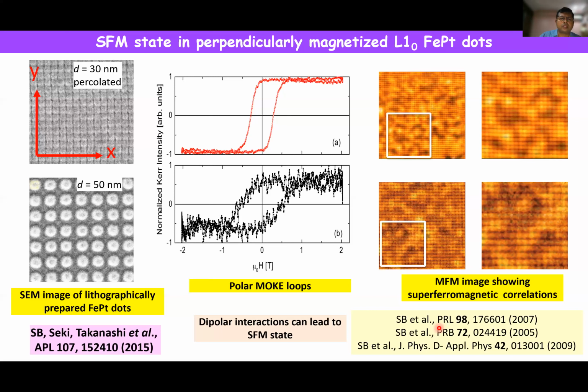So here I just quickly give a one-slide summary of some of our work in the so-called superferromagnetic domain state in magnetic dot arrays, where you try to couple them with dipolar interactions. Even if the dots are completely isolated, due to the dipolar coupling you can have superferromagnetic-like correlations. In this case, the dot arrays are percolating, so there is direct exchange interaction between the dots because they are touching each other.